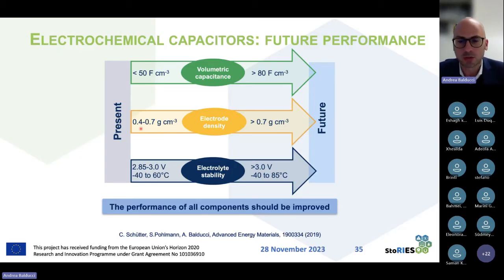But what we should also try to do is to increase possibly the temperature range of use of this system, because nowadays, due to the limited or lower evaporation point of acetonitrile, this system can work up to 60 degrees. They work very well at low temperature, but at high temperature, 60 degrees, they are not extremely performing. In the future, it will be important to keep the low temperature, but to extend the upper temperature to 85 degrees C. So again, this is an extremely challenging task that has to be fulfilled, because basically it is touching any component of the devices. But from the scientific point of view, this is also one of the most interesting, because of course there are plenty of possibilities to implement ideas, to try to develop new materials, and to try to bring these new materials into real systems.